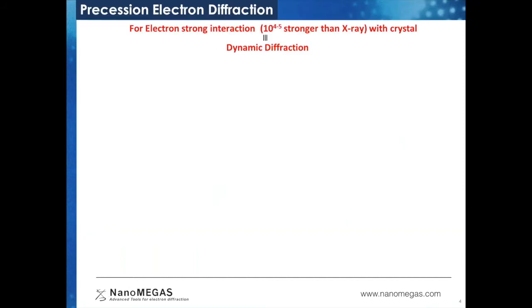Now, in the case of electron diffraction, the interaction of the beam with the crystal is extremely strong, and that makes the diffraction patterns more dynamical, meaning non-kinematical, which precisely means the intensity modulations in the diffraction pattern get messed up. Additionally, one can see more spots which should not be present due to systematic absences. Then there is a technique to minimize this dynamical diffraction in electron diffraction experiments, which is known as precession electron diffraction. The method was first proposed by Vincent and Midgley in 1994. I will show you later what the precession technique actually means, but first let's see the effect of